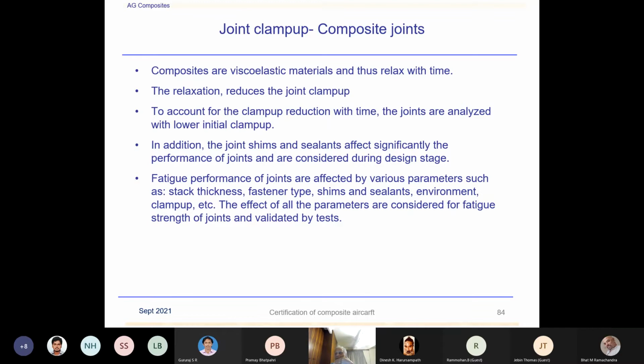So in order to test the joint, we will relax it for maybe a couple of 100 hours before you start loading in fatigue. If there is some relaxation, it would normally occur within that time mostly. And then of course it's a small reduction. And you start loading in fatigue, and fatigue will cause probably some more relaxation; there are shim, sealant, and all those effects you have to generate through the test data. So essentially it's the test which will take care of all the parameters, shim, sealant, relaxation, and then you will determine the fatigue life. Essentially it's a function of several parameters in the joint, which I'll be talking about while talking about the bolted joint. So I won't discuss much detail about it. I thought I'd just give a brief background about it.